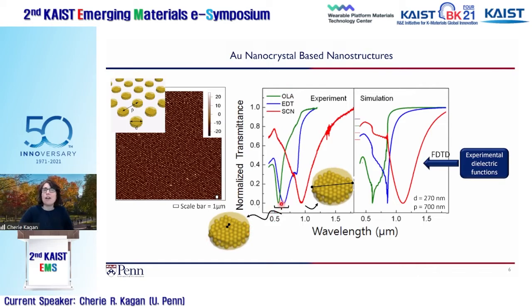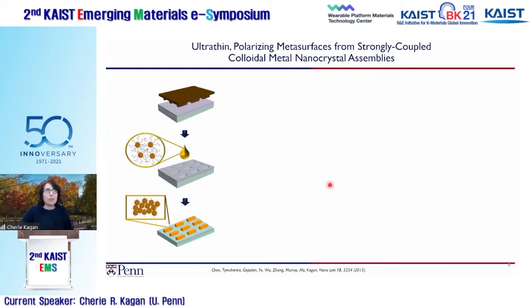If we exchange with ethanedithiol, it shifts a little bit to the red. So the environment is changing, but it's still largely characteristic of a system in which the particles are fairly well isolated from one another. But in the thiocyanate exchange, the resonance really shifts to the red, and it's characteristic of the geometry of the printed structure. We looked at this in playing with all sorts of different geometries to start with, and we can really think about how we would use this, and started to work on using this as a technique to make different, large-area printed optical metamaterials.